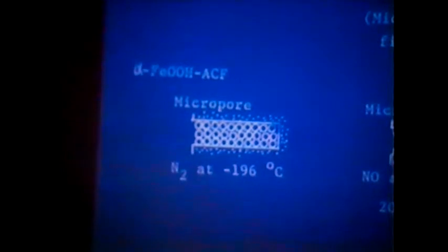The boiling temperatures of nitrogen dioxide and sulfur dioxide are near room temperature, so they are condensable on solids by physical adsorption or micropore filling around room temperature. But the boiling temperature of nitrogen monoxide is so low that we can't fix NO on solids by physical adsorption around room temperature. In such a case, we must use chemisorptive action.